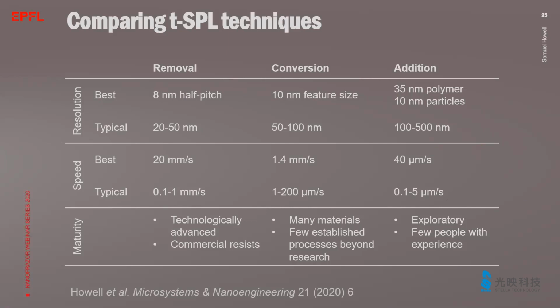In terms of maturity, the most mature technique is removal with a commercial resist, PPA, for which we have seen that many fabrication processes exist, and also the commercial resist is available. But for conversion, many materials have been converted in the literature by t-SPL, but only few established processes exist beyond research in universities. Addition of material is still in a very exploratory phase, with only few people that master this technique.